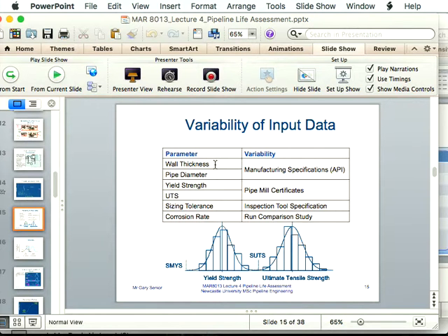Diameter is less of an issue, but yield strength varies quite a lot. It's quite important and it's quite useful to us. So if you have an X65 steel, API 5L X65, that has a nominal SMYS of 450 megapascals. If you looked at all of the material certs, what sort of yield strength would you actually get? Or what would the mean be, do you think? Min, max and mean, for example. So low point, mid point, max point. What do you reckon? I think the measured yield would be higher normally, because usually in the distribution that the mills provide, they use the lower yield strength.